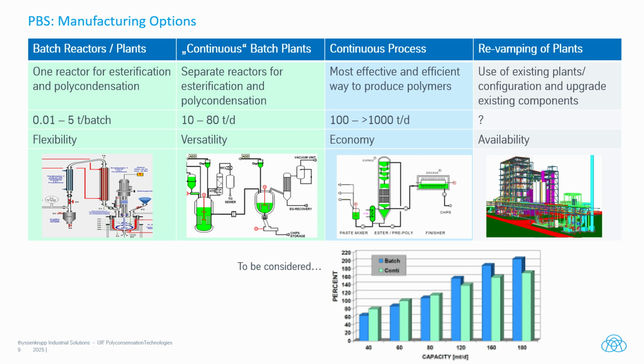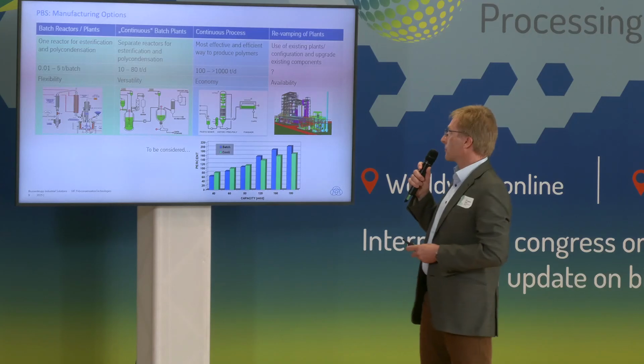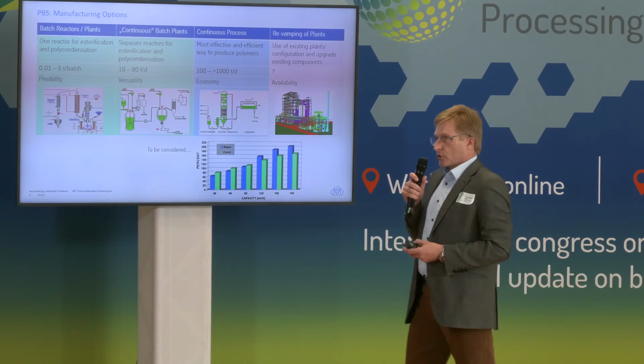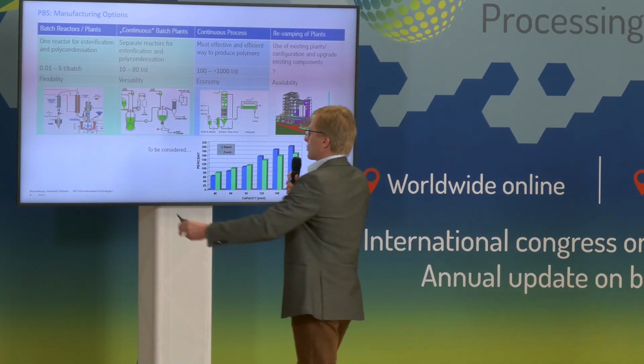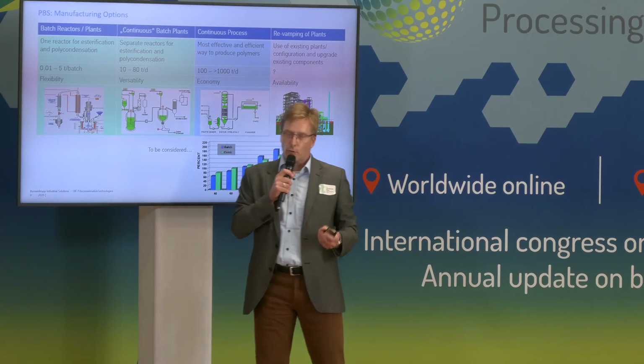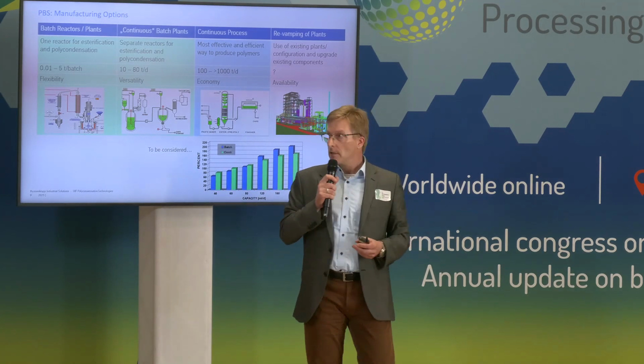So now let's look at how we can produce PBS. And this is always a question of scale. The most easy way to produce PBS is starting with a single batch reactor. You can do this in capacities from 10 kilograms up to 5 tons per batch, which is quite easy. You have an esterification reactor and a polycondensation reactor in one reactor.